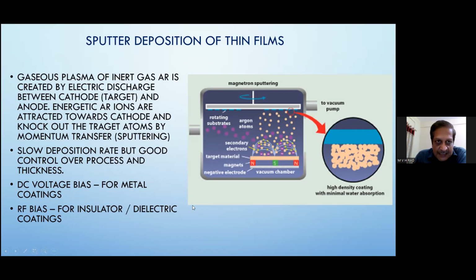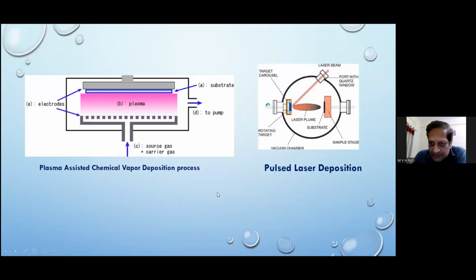So these are the different methods, and I just want to quickly go through. I already told about pulse laser deposition. The laser plume is generated by a laser beam, and it vaporizes locally. Maybe within 2 mm or 3 mm, or maximum 5 mm area is attacked by this laser, whatever the spot size of the laser. From that area only, material is evaporated, and it comes in the form of a plume and gets deposited.